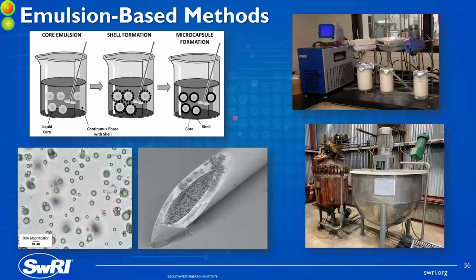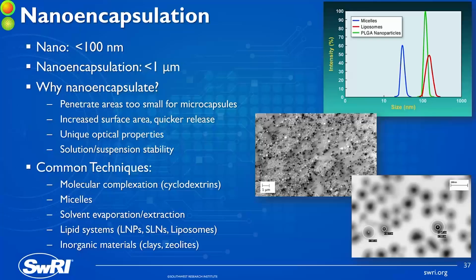But you can also go much smaller now than you can with co-extrusion or fluid bed coating or spray drying. So here we have a tip of a needle injecting small little, about 200, 500 nanometer size particles made using a solvent evaporation, solvent extraction process. So the emulsion-based processes, we can do matrix or core shell, and it bridges us over to nanoencapsulation.